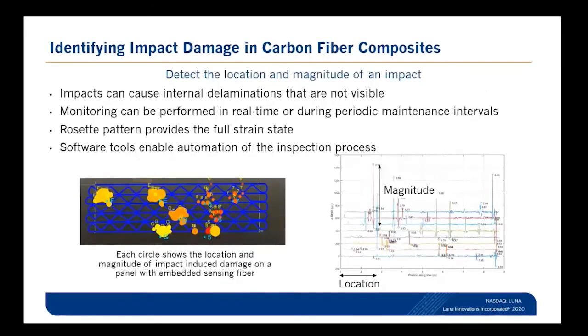Where that comes in handy is really, as I've mentioned before, when you don't know exactly where something may be occurring on your test article. And one of the good cases that can demonstrate this is when you're looking at impact damage on, say, a carbon fiber composite or any composite. Composites aren't going to necessarily transfer strain the same way that their metallic counterparts might. So what we'll do is we can put the fiber in a very dense pattern like is shown here in the bottom left,